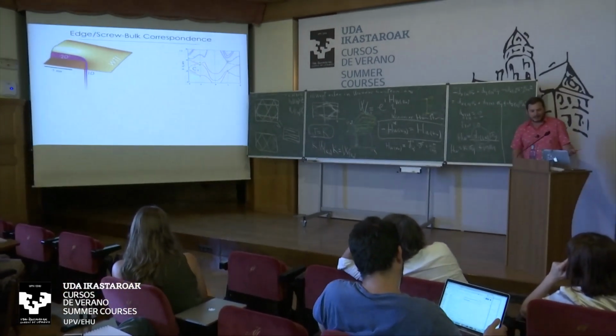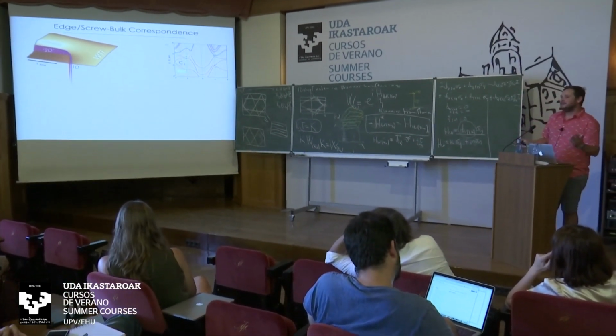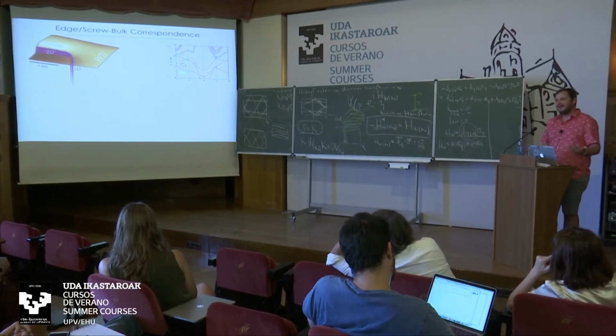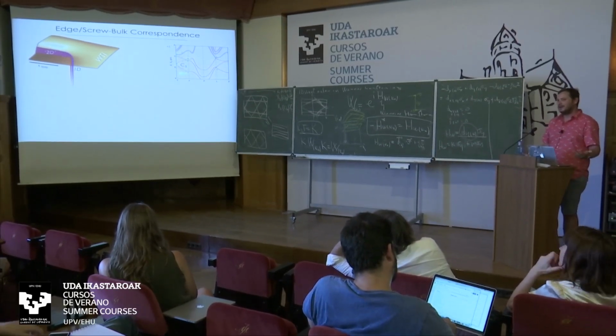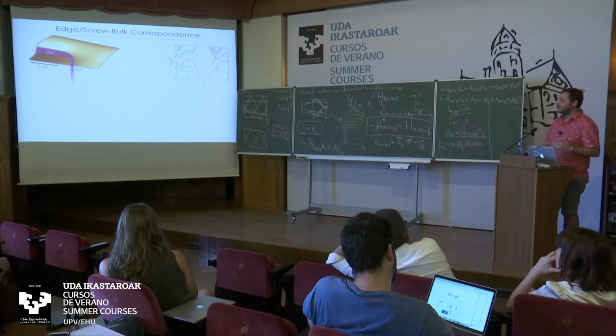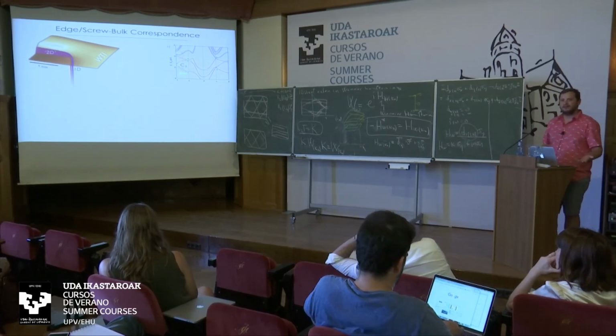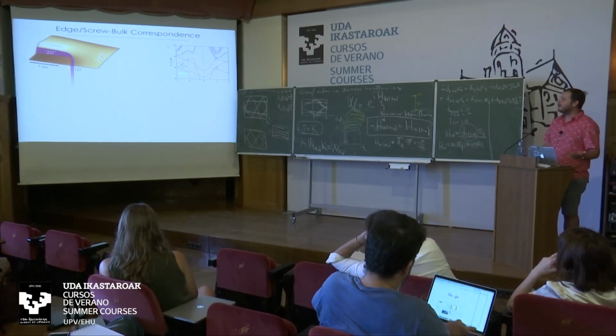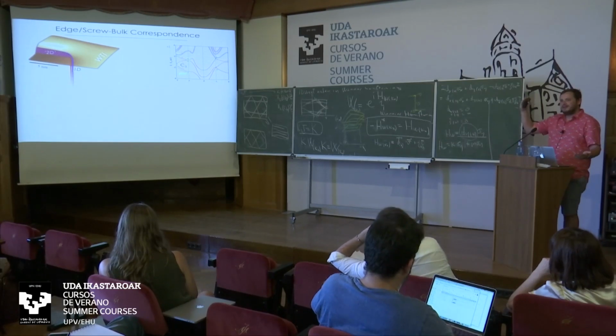So this is the weak TI interpretation. However, bismuth was never, in any DFT calculation, and there are quite a few, classified as a weak topological insulator. No one identified any weak indices in bismuth. Although it's kind of a natural candidate because we stack bismuth bilayers, which are 2D TIs.